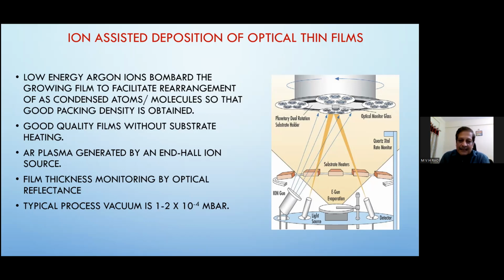So to convert an island growth process into a layer process, what we can do is use an ion source to give some extra energy. The islands are intentionally broken, so that the atoms vaporize again and get rearranged in a proper way to form a layer. So the ion assist gun basically